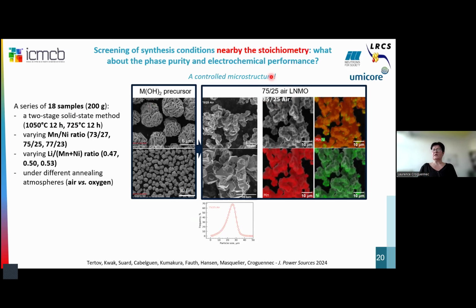And here, just to highlight, 75-25 corresponds in fact to the composition of manganese and nickel. So here we are in the stoichiometric conditions, air in the atmosphere. And so we have really varied the manganese over nickel ratio: deficiency in manganese, stoichiometry, excess in manganese. We have varied the composition in lithium: deficiency in lithium, stoichiometry, excess of lithium, and we have used different atmospheres, air versus oxygen.